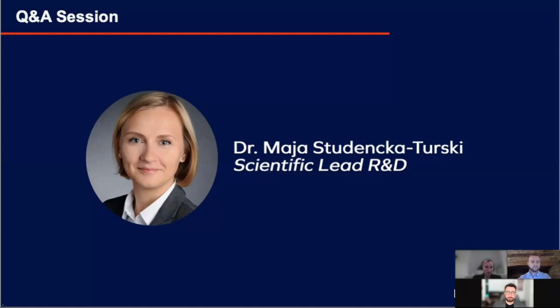If the amplicon is small, around 60 base pairs, then it obviously will work. If the amplicon is a bit longer, then we would recommend longer extension times. The entire time of 40 cycles would be around 45 minutes. But again, it depends on the ramping time. If you're using fast protocols, it will be faster, and if the ramping in your device is slower, then it will be slower. However, for most cases it will be under 1 hour, or around 50 minutes.